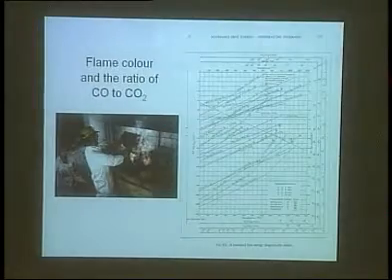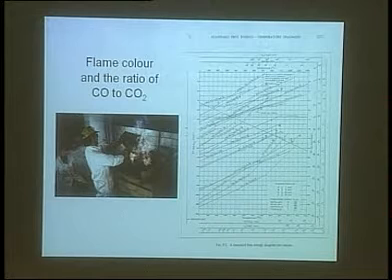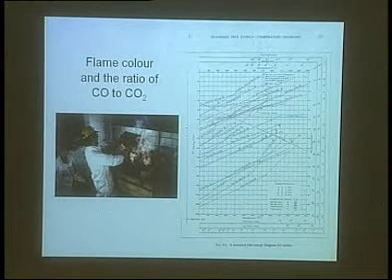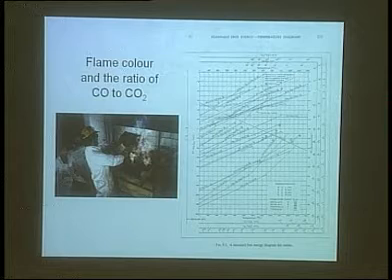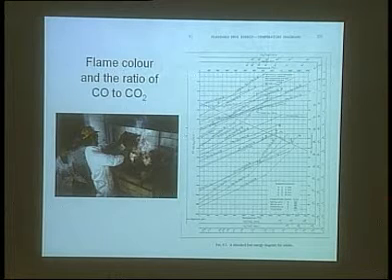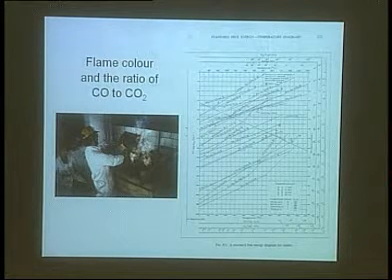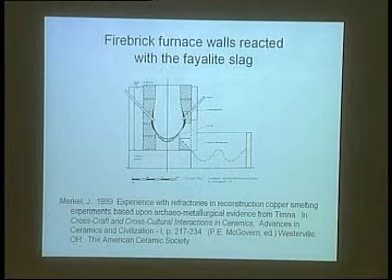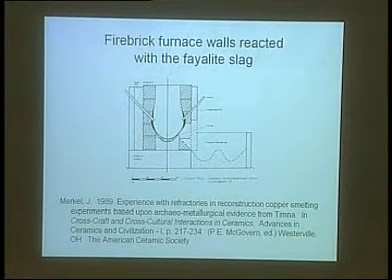In terms of CO2 and the color, again, that was all monitored. And looking at some of the thermodynamics behind it, we can see that conditions in the furnace were not only enough to reduce the copper, but also enough to reduce iron. So iron's one of those aspects that I want to look at now in the furnace, because the iron and the reactions in the furnace all tie together to characterize what was happening at this period for the furnaces.